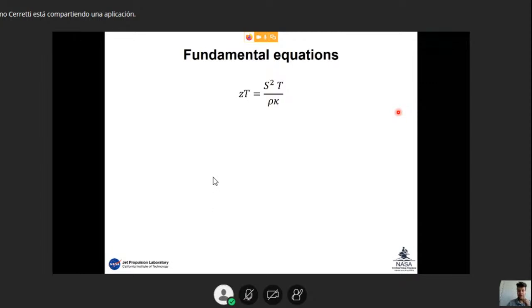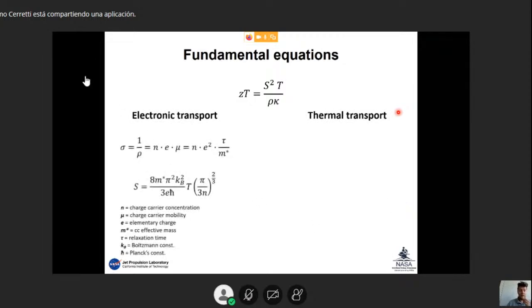So just to give you a brief overview of the main equations that are used, and to dig a bit more into the relations among all the terms that concur to the definition of the ZT, you can see the electronic transport and thermal transport. On the electronic transport side, sigma is the electrical conductivity, which is the reciprocal of the resistivity, and it's a function of the charge carrier concentration and the charge carrier mobility. And this can then be rewritten as the relaxation time over the effective mass of the charge carrier.